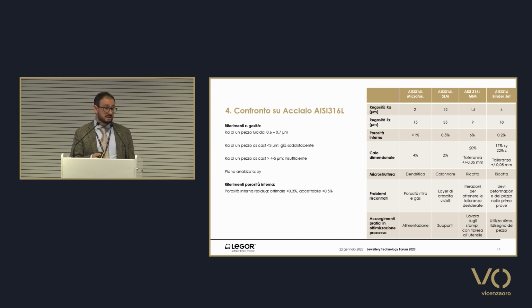Other relevant aspects of this table are the dimensional reductions. The reduction in size is also to be considered. With MIM, we have a reduction in volume of some 20%. In the case of the binder jet, we saw that this reduction in size depends on when the binder was added to grant the adhesion among the different layers of powder, and this is something that should be considered again when the item is, when this jewel is designed.